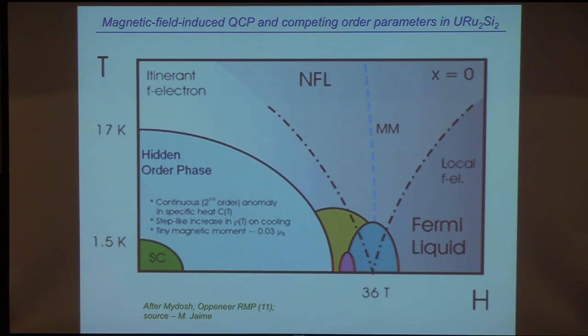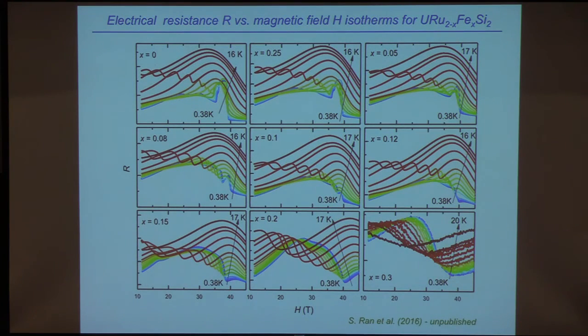This is another figure. It's kind of a cartoon, but it shows more clearly what's believed to be happening. Again, superconductivity is down here, hidden order in here. You get itinerant electron behavior here. This is the peak in the resistivity. This is the crossover to the Fermi liquid behavior, metamagnetic transition, non-Fermi liquid behavior in here, and this cascade of quantum phases at high fields. Now, interestingly enough, I'm not going to show you this, but if you substitute about 5% iron in here, you can remove all these other quantum phases and the hidden order and just produce one of them at this point right here. Okay.